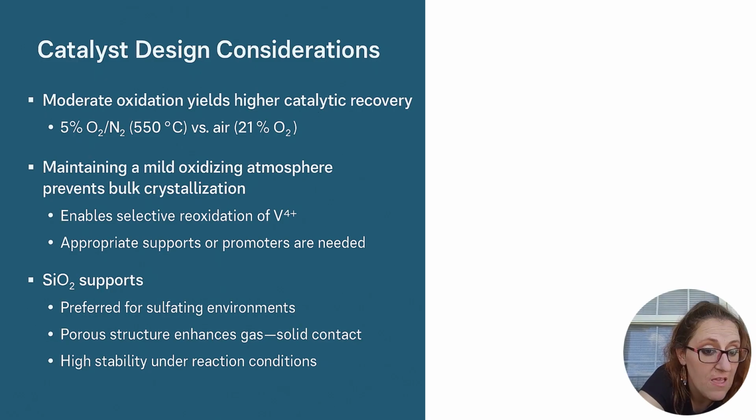containing vanadium sources, such as the active component ammonium metavanadate, NH4VO3, or vanadyl sulfate, VOSO4, which decompose upon calcination to form vanadium pentoxide. NH4VO3 releases NH3 and H2O, while VOSO4 evolves SO2, SO3, and O2, both routes yielding vanadium pentoxide as the active